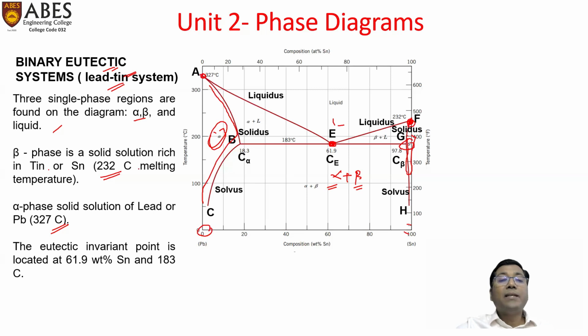This point is A. The eutectic invariant point is located at 61.9 weight% tin and 183 degrees Celsius. So 61.9 weight% tin is here, this point, and temperature 183 degrees Celsius, we can mark over here. This point we can locate. This is the eutectic point or invariant point. At this point, what we discussed just now, this liquid will transform into alpha plus beta. Since we are discussing the eutectic system, this eutectic point or invariant point is of prime importance.